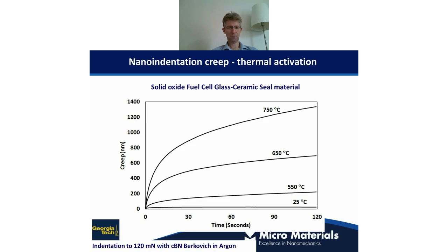In this case, we're using a cubic boron nitride indenter and an argon purging environment to restrict sample oxidation, and also to work above the oxidation temperature of 500 degrees for diamond. And this is looking at a solid oxide fuel cell material. And what we can see is that it doesn't creep at all at 25 degrees. It doesn't creep much at 550, but then over that range, it dramatically increases its creep. So this restricts its performance.